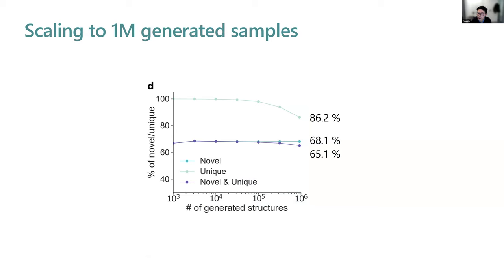In addition, we also hope to look at how our model performs if you scale up the generation to a million structures. We actually found that, for example, the uniqueness only drops to 86% after we scale to a million crystals, meaning for these million crystals, 86% of them are all different. And in addition, the novelty stayed the same at around 68%, meaning the majority of the structures generated are novel. So these are the overall results for generating novel and stable materials with our model.